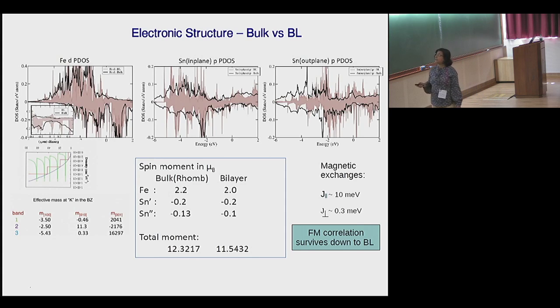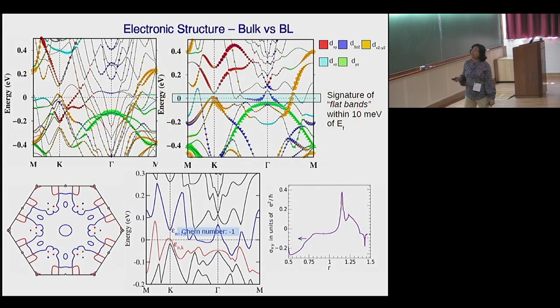It is a ferromagnetic object with ferromagnetic exchanges within the Kagome layer and out of the Kagome layer, which survives down to the bilayer. And if you look at the electronic structure, this is the electronic structure of the bulk material, and this is the electronic structure of the bilayer. Compared to the bilayer, in the bulk there were a lot of states, where the fatness was proportional to the iron D character. So there are a lot of flat bands which show up in the electronic structure of the bulk, which gets far more cleaned up if you go to the bilayer limit.